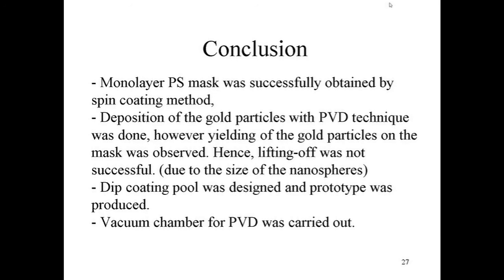A monolayer polystyrene mask was successfully obtained by the spin coating method. Deposition of the gold particles with the physical vapor deposition technique was done, however, yielding of the gold particles on the mask was observed. Hence, lifting off was not successful due to the size of the nanospheres. A dip coating pool was designed and a prototype was produced. A vacuum chamber for physical vapor deposition was designed. Thank you for your attention.